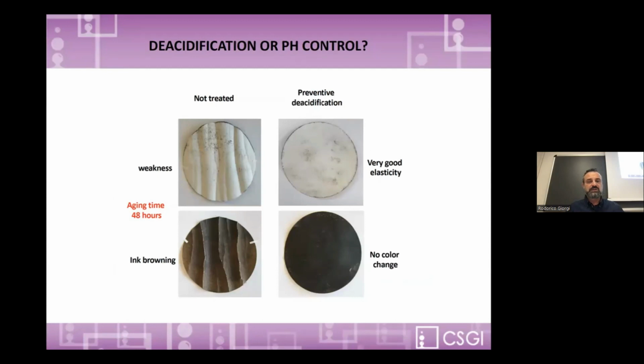And this is what we observe. It is impressive because only 48 hours are enough to completely change the mechanical properties of cellulose, to have discoloration of inks, but above all, paper has completely lost the mechanical properties, the resistance to tensile strength and elasticity. Exactly the same sample that was treated with nanoparticles to reach pH around neutrality, exactly the same inks, did not produce any of these effects, preserving good elasticity of paper, good mechanical resistance, and no color change.